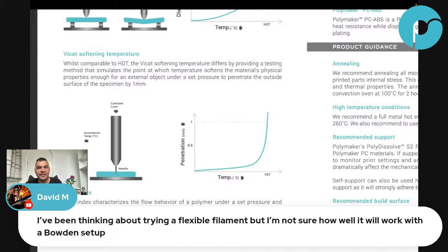Well, one thing you can do is make your 3D printer not require that much force to extrude. So instead of extruding with a lot of force, you extrude with a material that is very liquid, not very viscous. You do that by increasing the nozzle temperature, or increasing your nozzle size, or reducing friction in the nozzle. So anything that would lower the amount of force required.